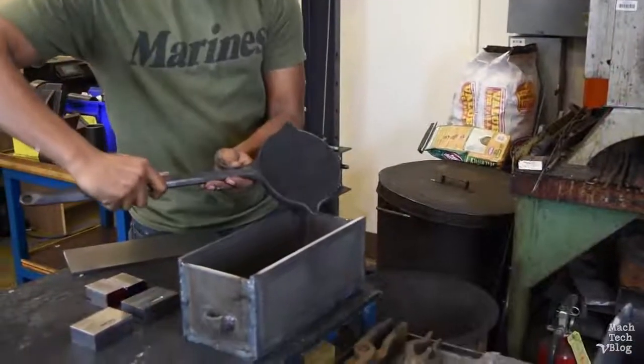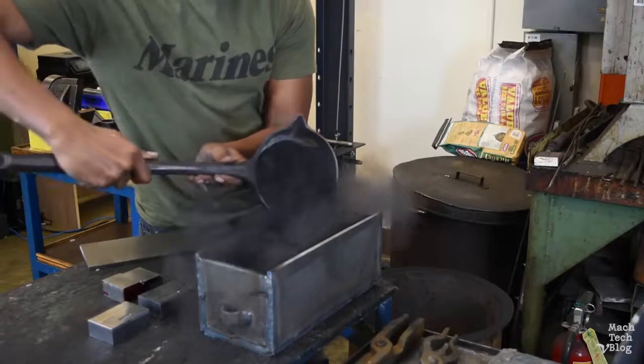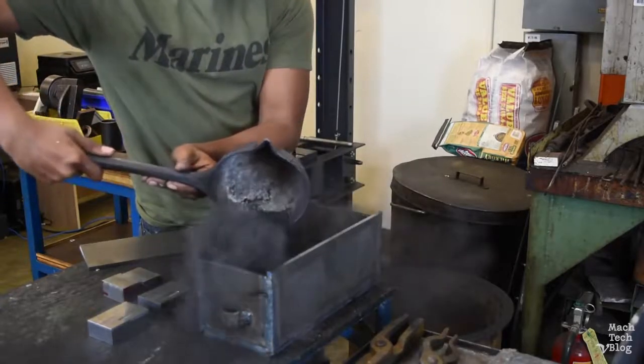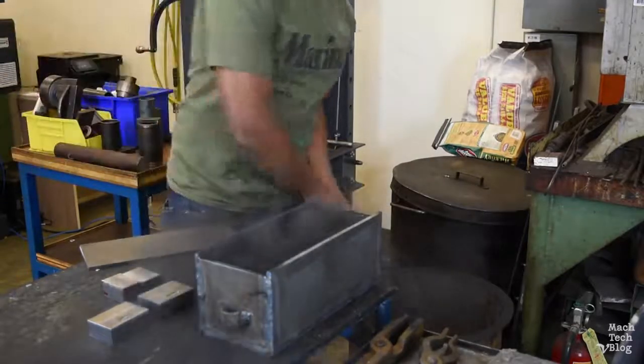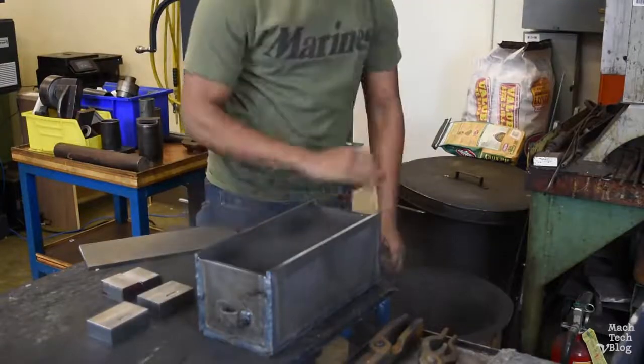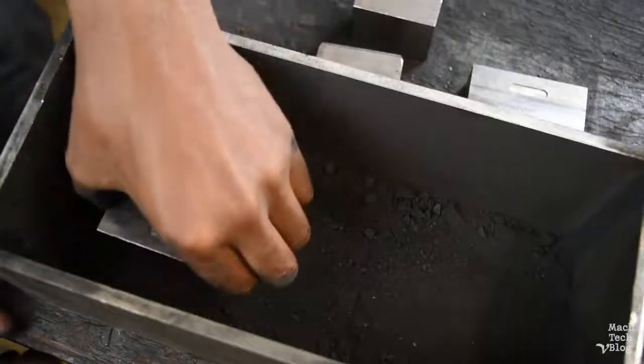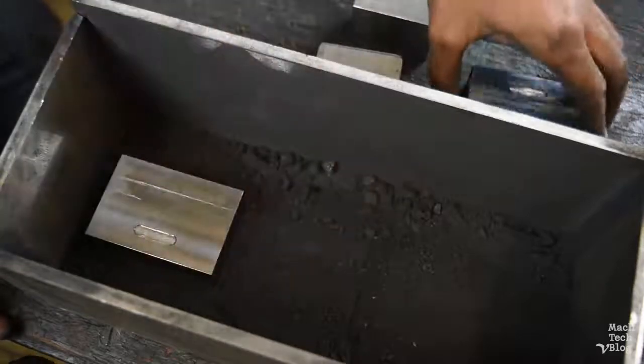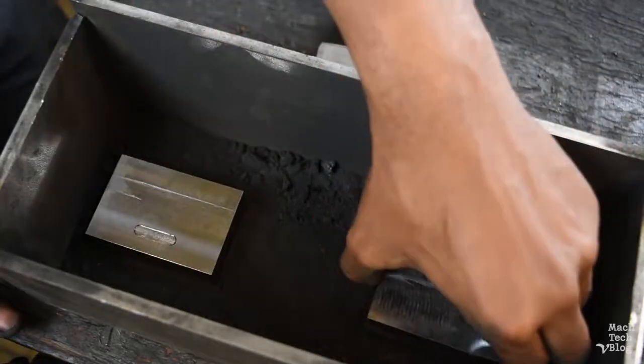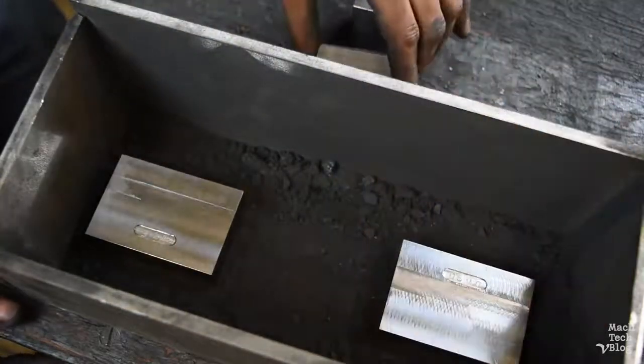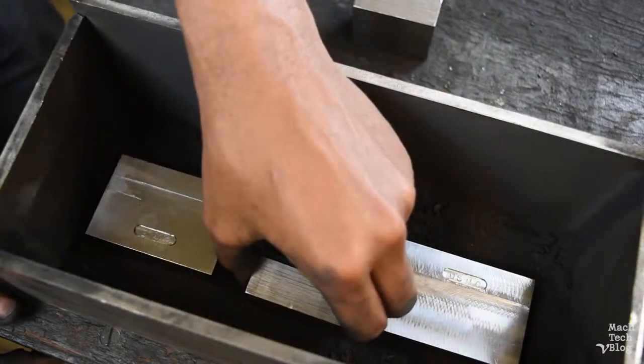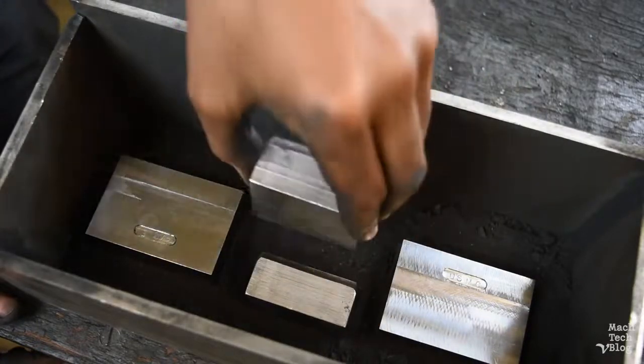Lay down about an inch of carbonaceous material in a steel box with a tight-fitting lid. Yes, we really are using broken up charcoal briquettes because it actually works pretty well. Arrange the blocks so that they're not touching each other or the box. Go ahead and put in 1 or 2 pieces of 1018 steel scrap so we can test the hardness later without putting divots in the finished parts.